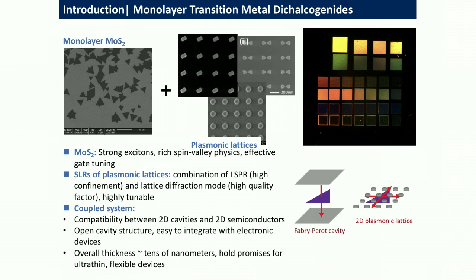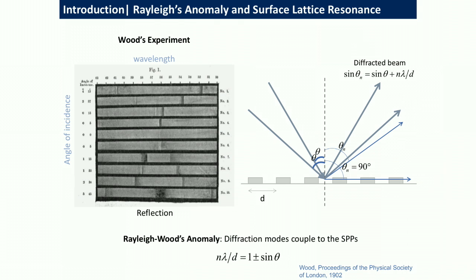So after many iterations, we realized that if we can make a crystal of plasmons, so we pattern these metal nanoparticles, then at each site you have these surface plasmons, and they can start to oscillate together and show collective modes. The idea was that we can utilize the very strong local confinement at each particle combined with this collective, what is called lattice mode, and hopefully get much better properties compared to a single particle.